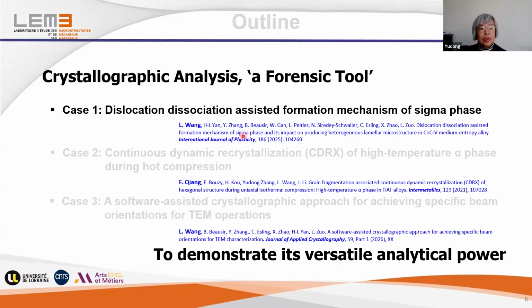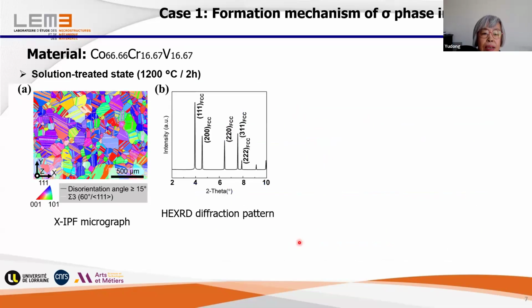Now I come to the first case study. This is regarding the phase transformation from FCC phase to sigma phase in a medium entropy alloy. This study is part of the PhD work of Luda Wang, and we have a paper published last year concerning this topic. In this work, we use this medium entropy alloy with these elements and such composition.